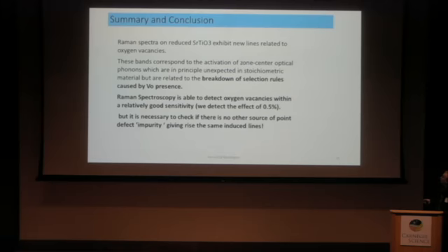But it's necessary to check that you have no other source of point defect or impurity, because this kind of defect can give rise to the same induced line.